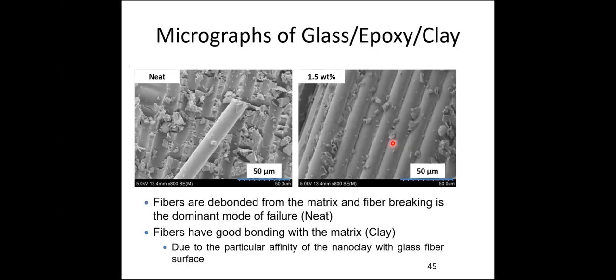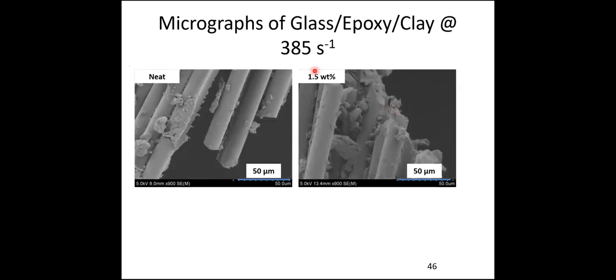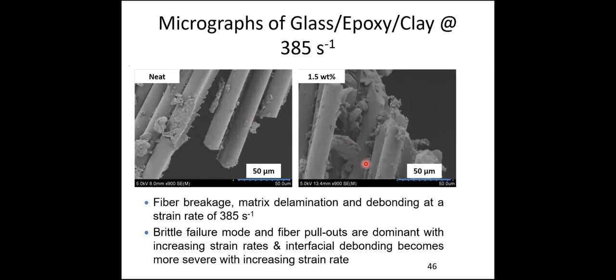Again, this is the micrograph of glass epoxy clay. So this is neat. You can see a fiber breakage, but for the clay samples, you can see a strong bonding of the epoxy clay with the fiber. So this is what we could see. Again, at high strain rate, we could see a fiber breakage and complete debonding of fiber from the matrix.